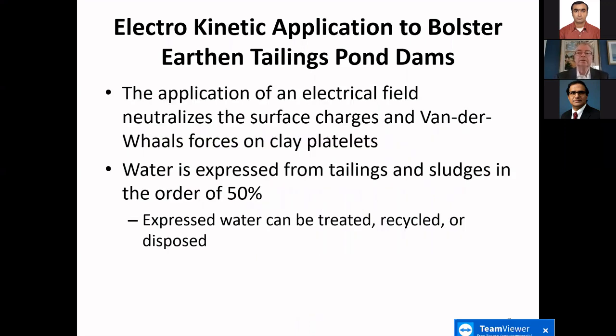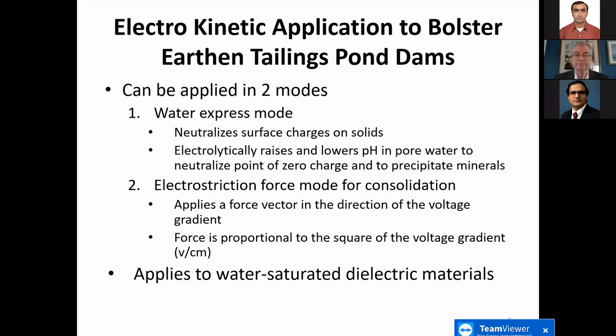The application of an electrical field neutralizes the surface charges and van der Waals forces on clay platelets as well as other non-conducting materials. Water is expressed from tailings and sludges in the order of about 50%. So we get an immediate volume reduction of about 50%. The expressed water can be treated, recycled, or disposed. So next slide.